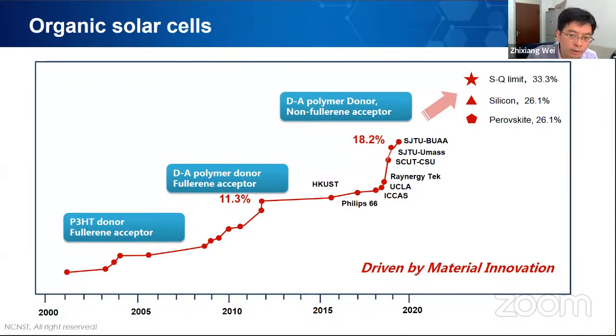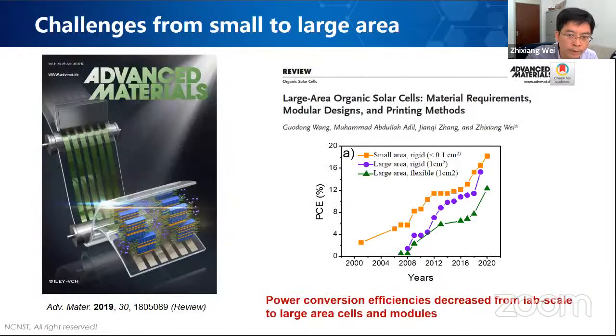Therefore, there is a really big requirement from, for example, the laboratories, people want to push this kind of technology from small area to large area printing. We wrote a review two years ago, and if you look at the efficiency, normally if you're doing small area on rigid substrate, efficiency is high. But if you're doing large area rigid or large area flexible, you see their efficiency actually decreased a little bit, and especially for the large area flexible ones, it decreased a lot. Therefore, you can see the power conversion efficiency decreased from lab scale to large area cells and modules.